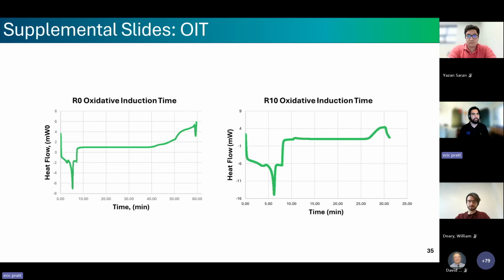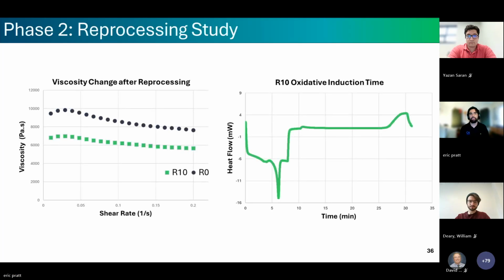So for our results of this study, between R0 and R10, the zero shear viscosity dropped by roughly 29%, which translates via the power law relationship to about a 9% reduction in molecular weight. And yet the tensile properties stayed statistically unchanged across all 10 cycles.